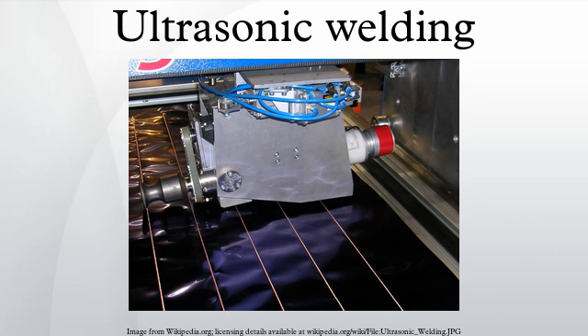Process. For joining complex injection molded thermoplastic parts, ultrasonic welding equipment can be easily customized to fit the exact specifications of the parts being welded. The parts are sandwiched between a fixed-shaped nest and a sonotrode connected to a transducer, and a 20 kHz high-amplitude acoustic vibration is emitted when welding plastics.